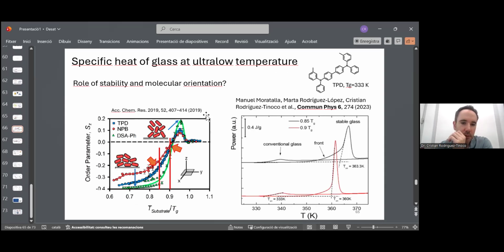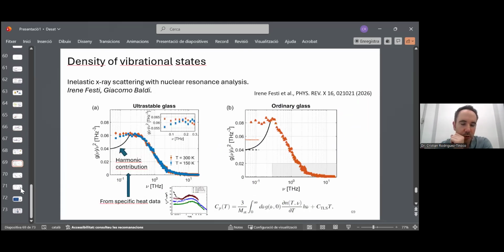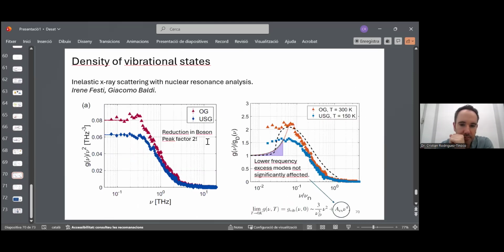Okay, so I also have something here about the experiments performed by Giacomo Baldi, but the conclusions are basically, well, I don't know if you were present in the talk by Giacomo Baldi in the last seminar, that in the case of the ultrastable glass, we observed a reduction in the boson peak by a factor of 2 with respect to the Debye level. In this case, we only studied the ultrastable glass, so in principle, we concluded that the reason for this decrease was the increased density of the system, but strictly speaking, we cannot discard the role of anisotropy here.